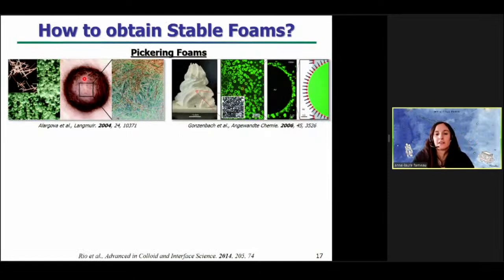But the main question is how to obtain stable foams. You have different examples in the literature. The first one is called Pickering or Ramsden foams. You can have stable foam because the solid particles adsorb at the air-water interface and form a solid layer surrounding the bubbles. And then you can really have stable foam for months or even years with these solid particles.